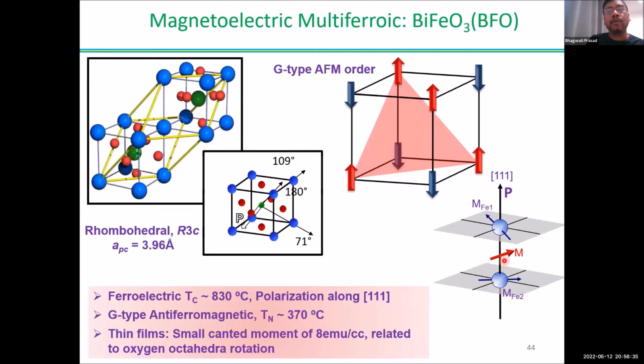Okay, so we have used the multiferroic material BFO, which has both ferroelectric and magnetic ordering, which is basically a G-type antiferromagnetic system. You can see both orderings at room temperature. But when you make a thin film, you see a small canted moment, which is around 8 emu per cc, which is really small.